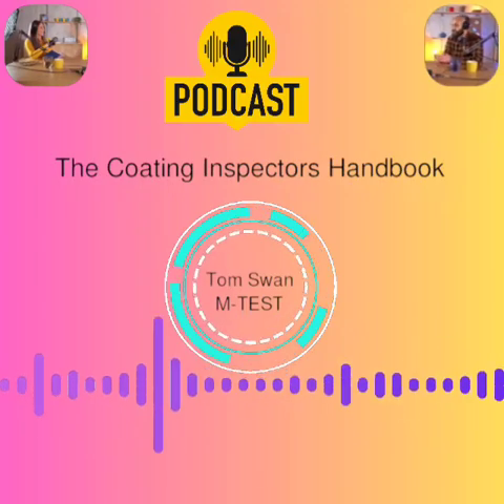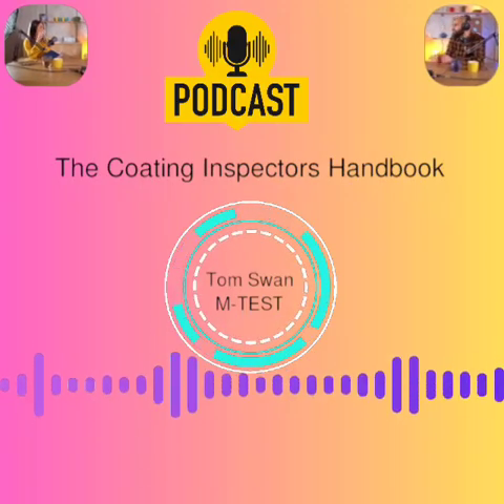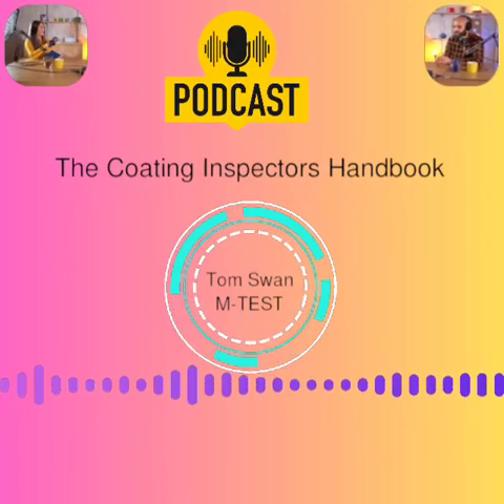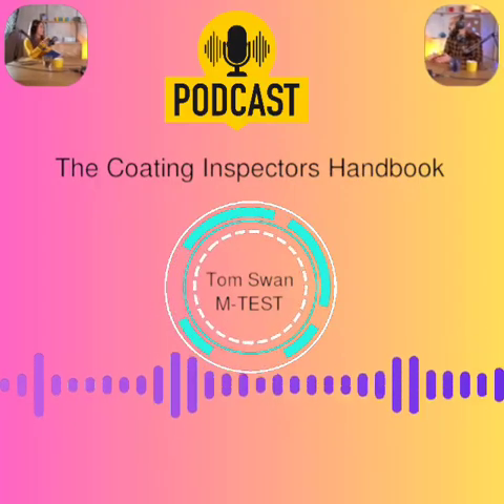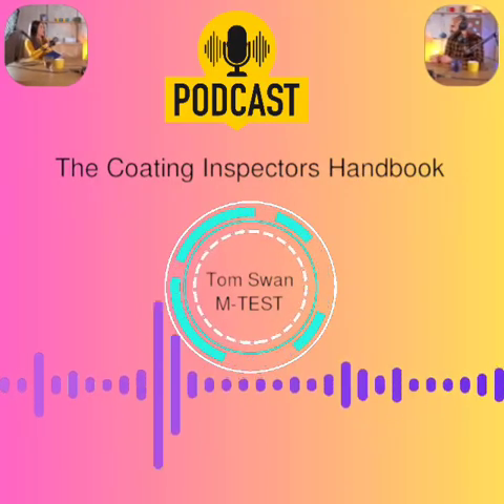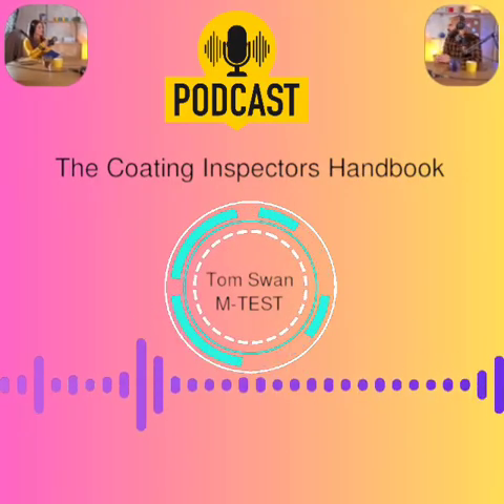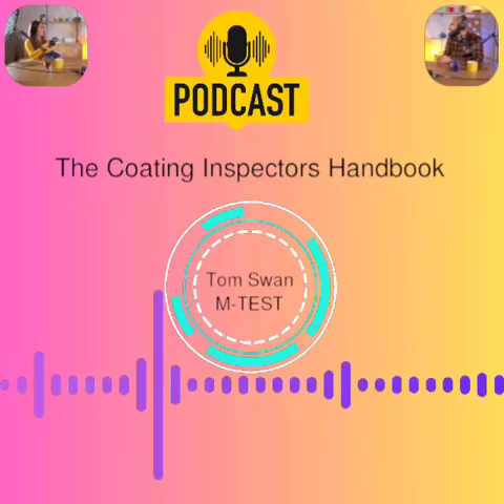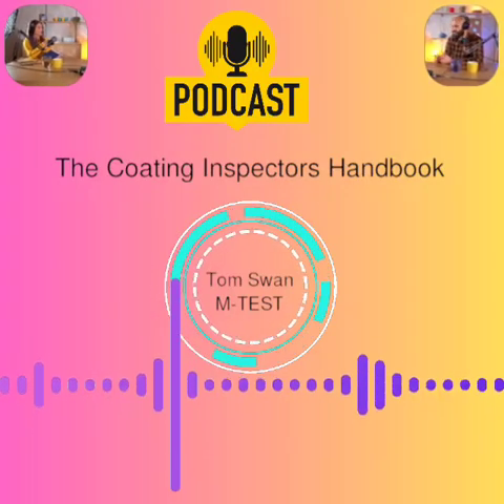To score around the dolly or not? Spec should say. ASTM is cautious: scoring can cause cracks, lower psi. Not scoring might get influence from adjacent paint, higher psi. ISO requires scoring. General advice, don't score unless paint is very thick or rubbery. Discuss if spec is silent.